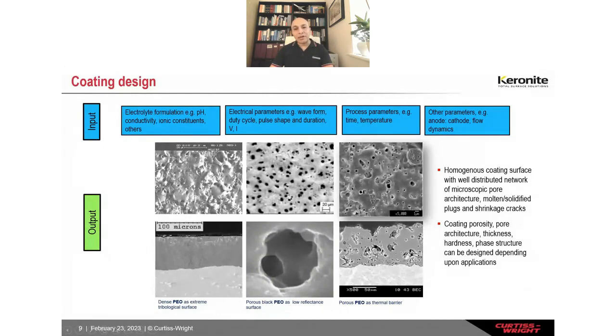For example, on the left-hand side, you have a highly fused alumina surface, very dense. The bottom is the cross-section of the same, quite a thick, about 100 micron coating, extremely well adhered. We call it an atomically bonded coating to the substrate, very uniform, right? In the middle picture, you can see a highly porous coating architecture. So you are preparing porous scaffolds for various reasons. It could be to deposit a secondary layer, such as paints or powder coats, on top of it, or this could be with deep pore architecture, like an optical light trap for space missions, for cameras, maybe for optical housing, where it gives a very, very low optical reflectance.